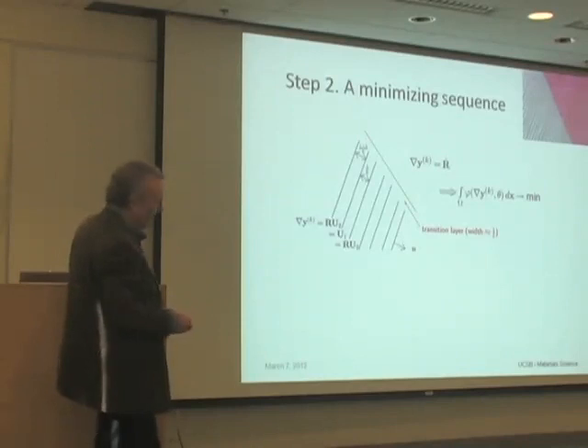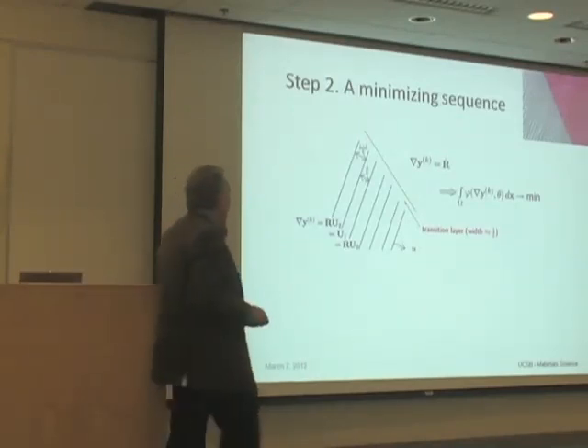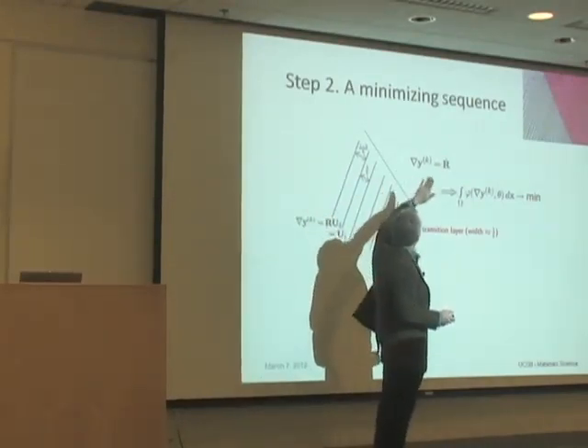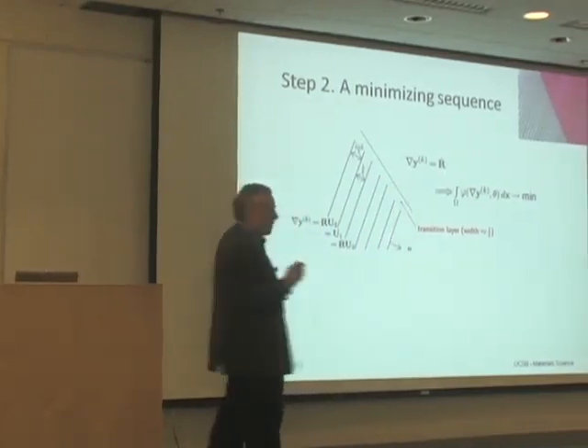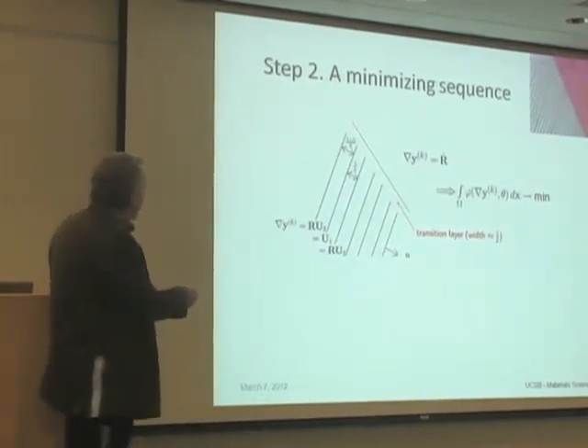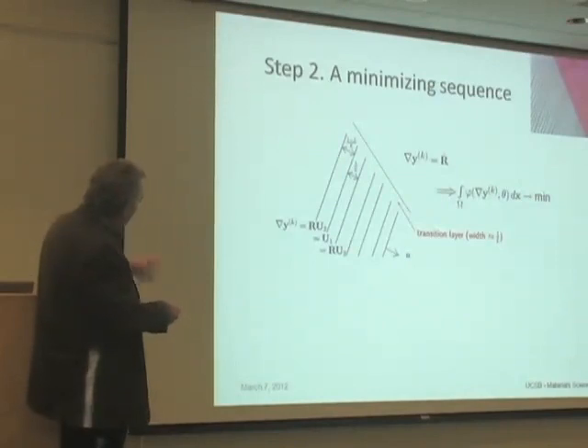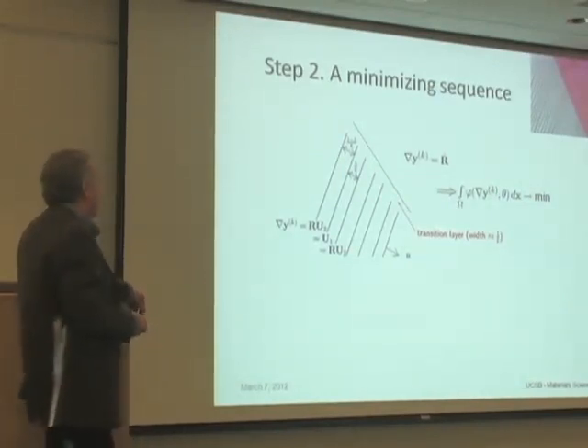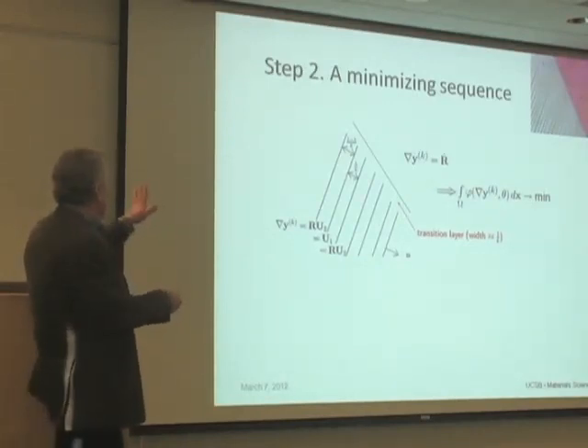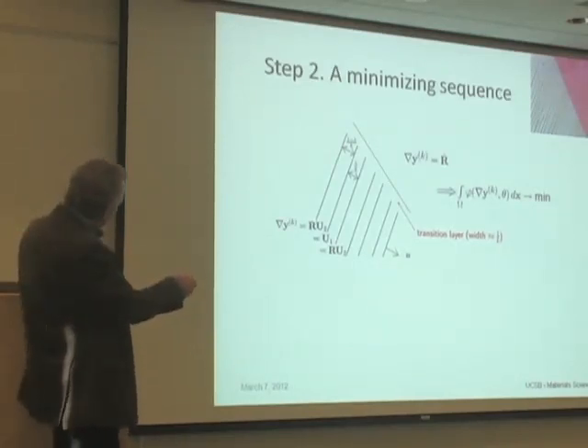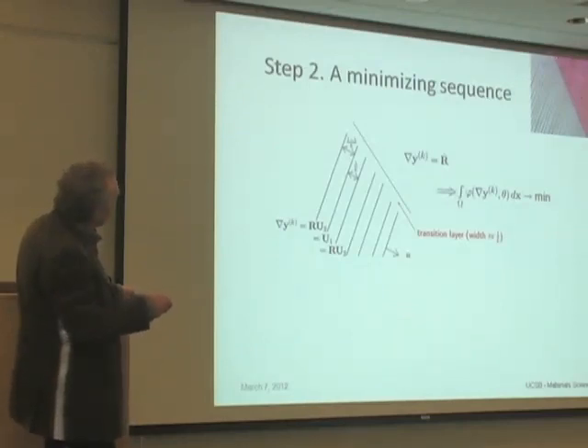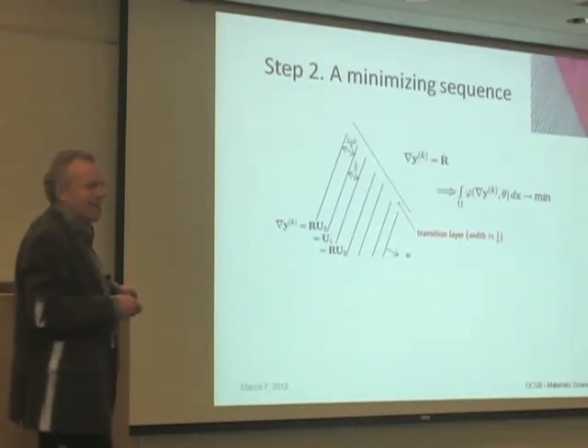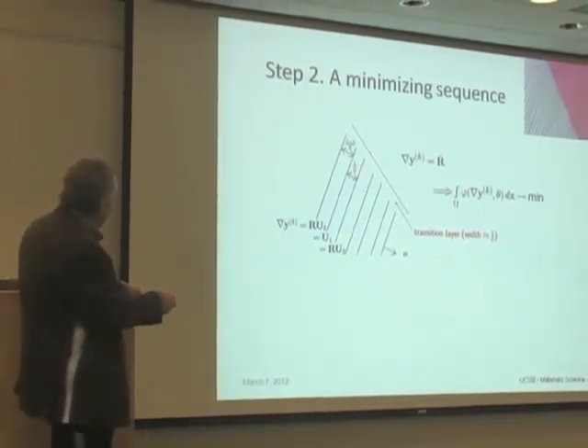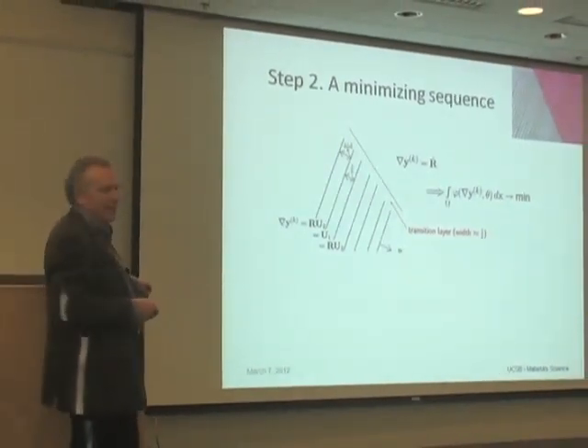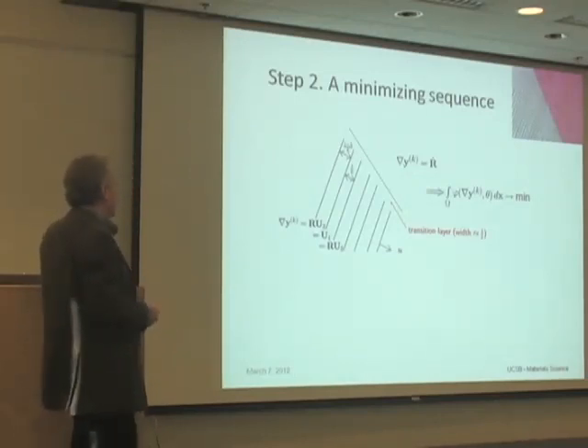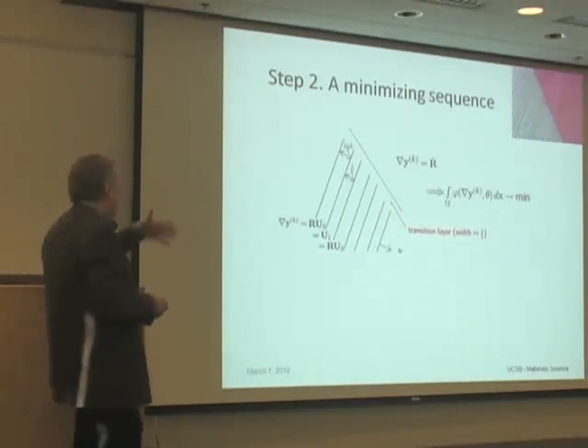So the point is the following. There's a normal to this. If I arrange this interface to have just the right normal, and I choose this lambda to be just the right volume fraction, then it's possible to reduce that elastic energy to zero, to drive it to zero, by making the twins finer and finer. So that's a mathematical calculation. It's just a matter of putting in a transition layer and seeing what happens when you make this finer and finer, and you get some result. But you have to take a particular normal and a particular volume fraction. If you take that normal and you compare with the normal to that surface, you get really nice agreement. And if you take the angle between those twin bands and the interface and compare with that angle, you'll get super nice agreement. It's been done many times in many different martensitic phase transformations. It's basically called the crystallographic theory of martensite. I'm just explaining it in a more energetic way than it's usually explained.